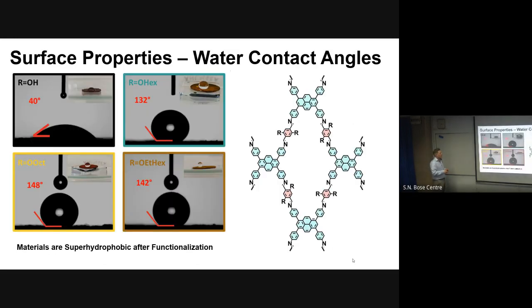Okay, so what we then next did was, we wanted to learn about the surface properties. So we measured some water contact angles. In the case of the first material, we pressed the pellet. This was not so successful for the other three materials, so here we coated some double-sided tape very smoothly. It's not so easy because your contact angle can depend a lot on the way you prepare the materials. There's some roughness, and if the surface is rough, you will automatically get a higher contact angle, and it's unavoidable.